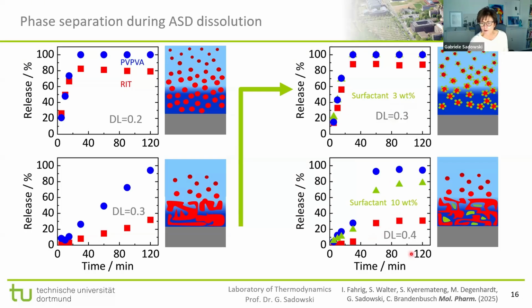What you see here is drug load 0.4. The idea was, if we go from 0.3 to 0.4, we should maybe also increase the amount of surfactant, from 3 weight% to 10 weight%. But unfortunately, this does not work. We have similar behavior to the one we had here with a drug load 0.3 without surfactant. The API is only released to a very small amount, only about 30% is released, the other part is not, whereas the polymer is released, and the surfactant is not totally released. So what happened here? The surfactant did work at 3 weight%, but it doesn't work at 10.